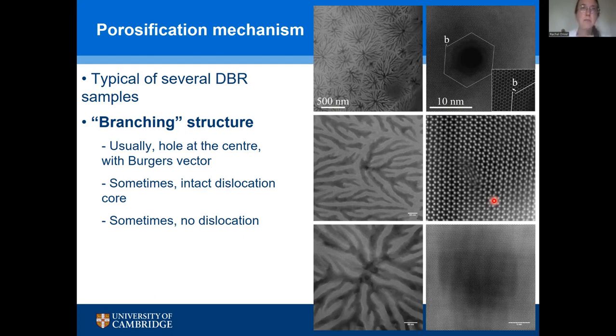So because people are currently really interested in tiny micro LEDs for augmented reality and virtual reality headsets, and really, really mini micro displays with LED sizes on the few micron scale, growing red nitride devices has suddenly become a really hot area. And it turns out that we can improve the growth of red emitting nitrides a lot by incorporating these porous underlayers, which essentially make the substrate compliant and allow us to get more indium incorporated, because the porous layer is taking up some of the strain in the structure.